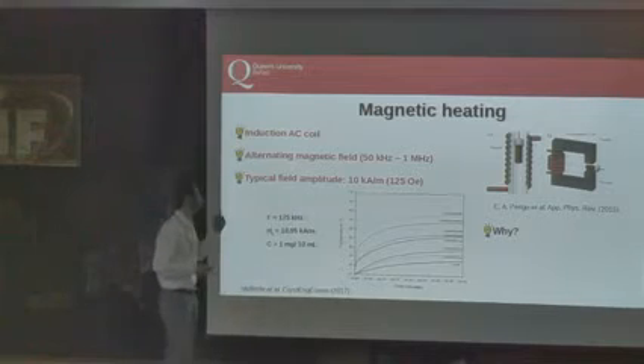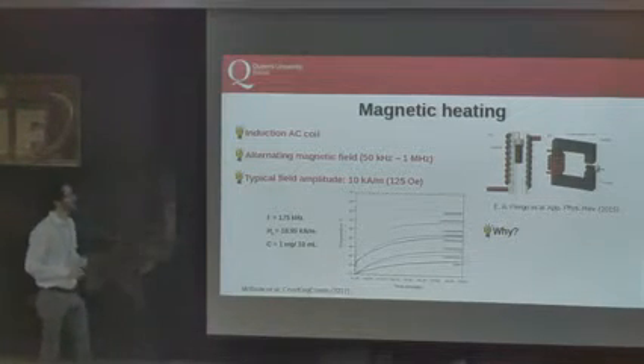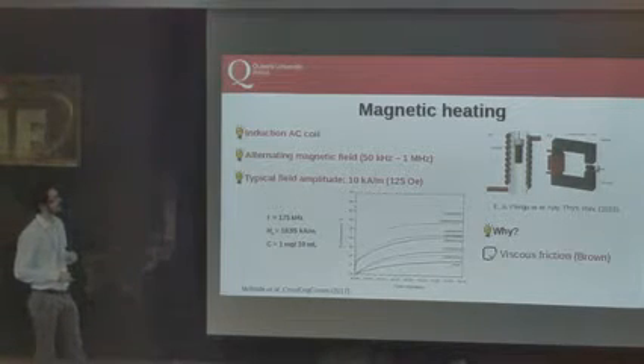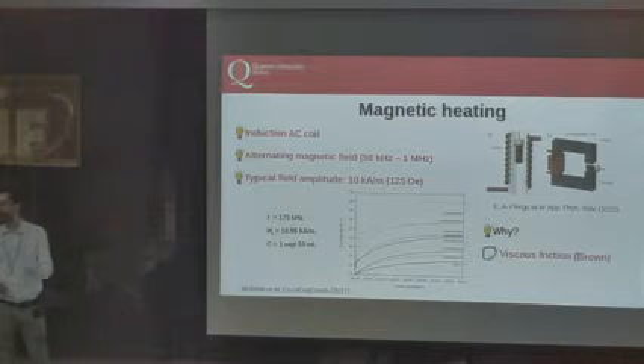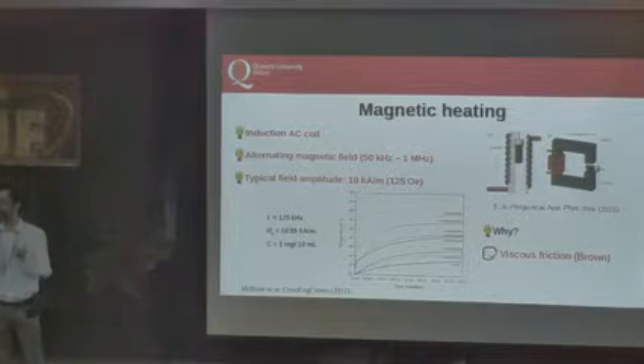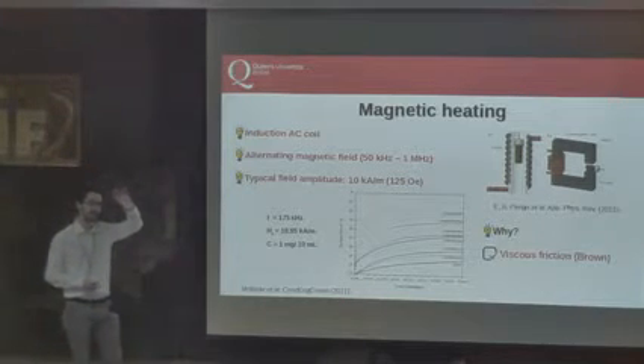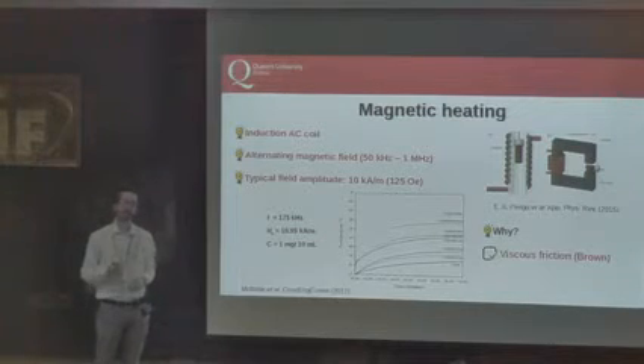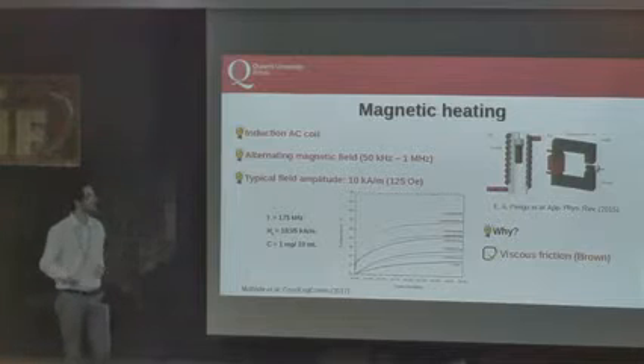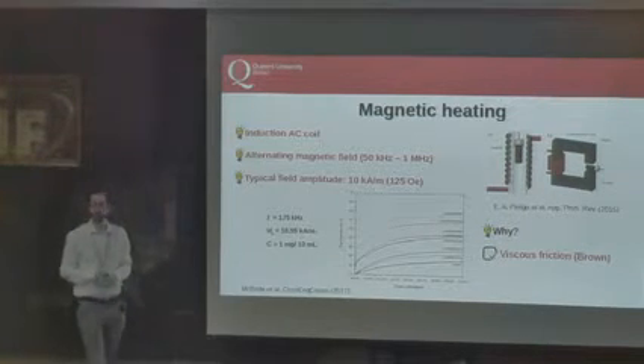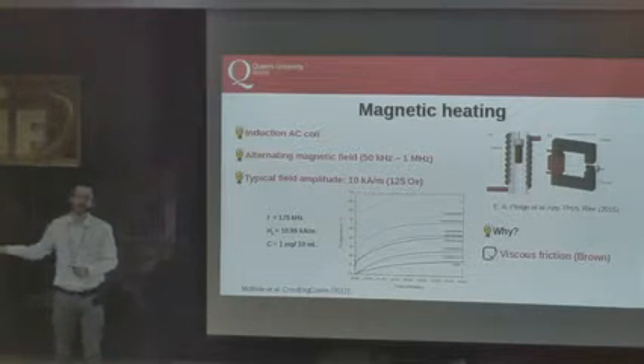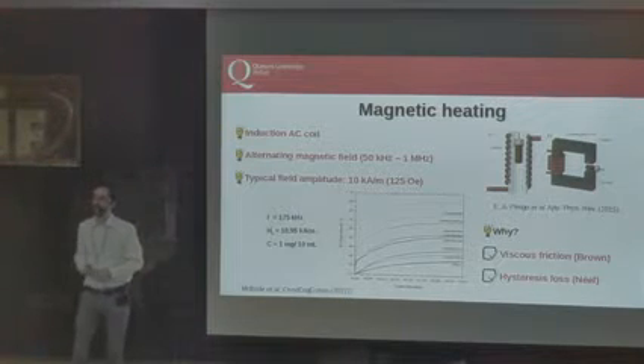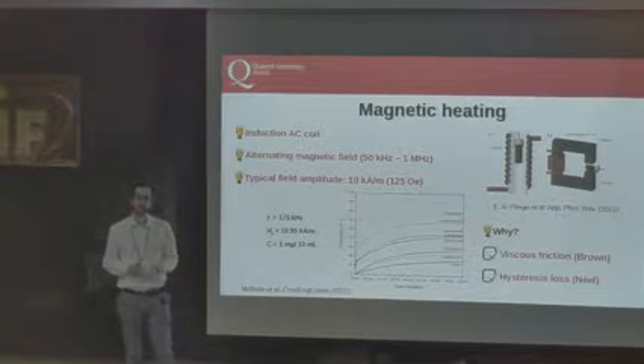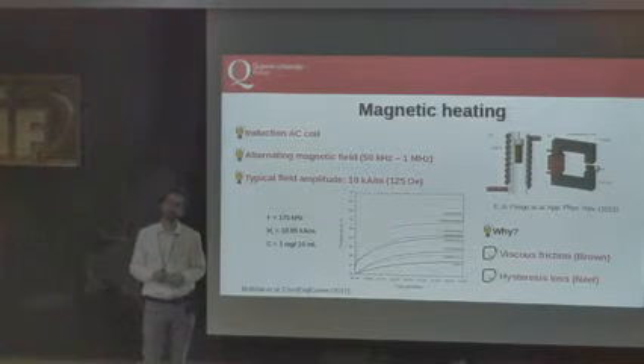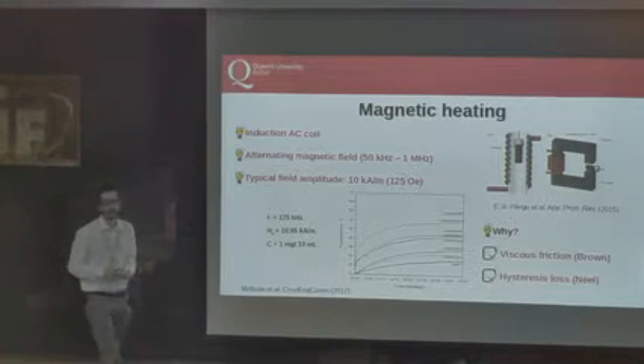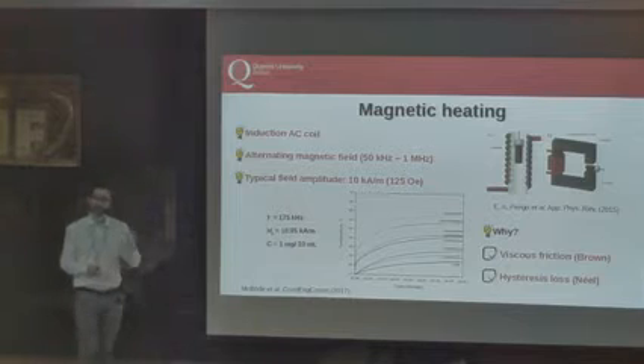The question is, of course, why these nanoparticles heat up, and here I use what I previously explained. There are two types of mechanism. The first one is the viscous friction: the particles rotate like rigid bodies in a viscous liquid like water, and so some energy is dissipated as friction. The other way is dissipation through hysteresis losses. There is a coherent change of magnetization driven by the external magnetic field, and this is due to the Néel mechanism. So those are the two main mechanisms.